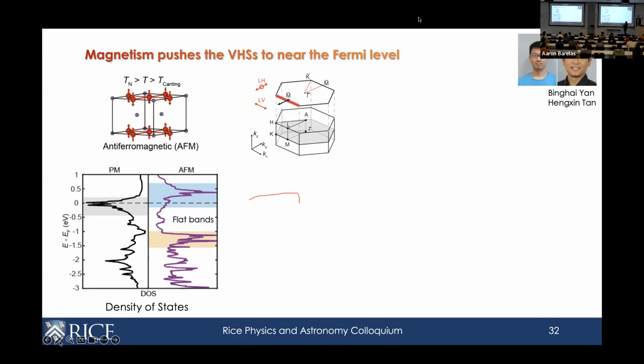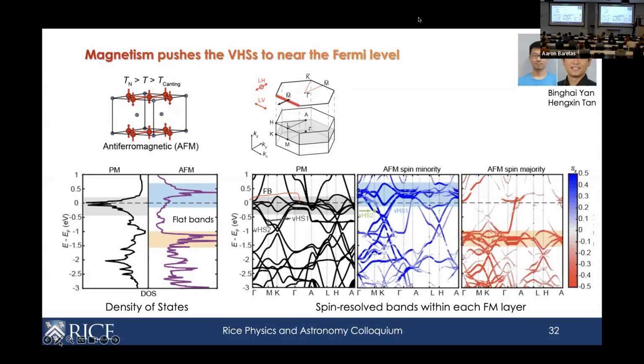So if you look at the density of states, this is the electronic density of states. If they calculate this for the non-magnetic phase, they see a really large peak here at the Fermi level. And then when they calculate that for the AFM phase, they can see the peak splits into two, right? How do you understand that? It turns out that peak corresponds to a large flat band in that region. So this is the angle-resolved or momentum-dependent density of states, or band dispersion. And you can see that this bunch of flat bands actually corresponds to this peak in the paramagnetic, non-magnetic calculation. And then when you lower into the AFM order, it splits into two. How do you understand that?